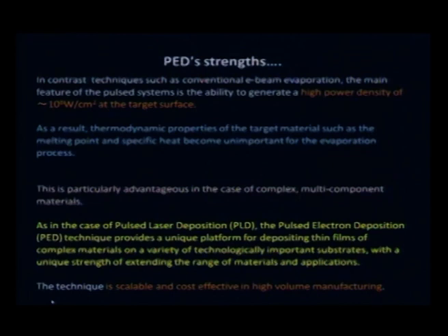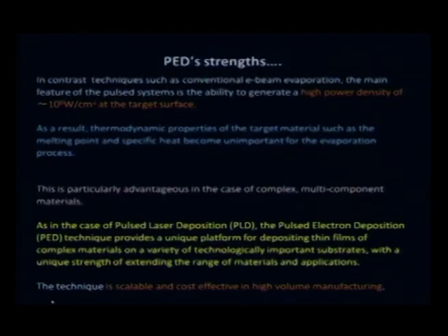There are some issues which act as strength for PED compared to PLD. Therefore it is better we familiarize why PED stands out in many ways compared to the most established PLD technique. In contrast to other techniques such as conventional electron beam evaporation, the main feature of this pulse system is the ability to generate a high power density of 10 power 8 watt per centimeter square at the target surface.